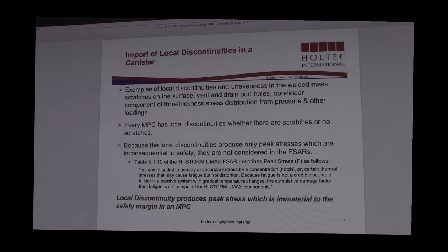And that's an important technical point, which will, as we go forward, influence the licensing aspects. But again, just to summarize that technical point, the surface scratches on the MPC are by code definition examples of local structural discontinuities, which means that they are local stress concentrations which are only capable of producing peak stresses. And peak stresses are only a concern from an ASME code design standpoint for fatigue and brittle fracture, and neither of those failure mechanisms are credible with respect to the MPC canister and its design.